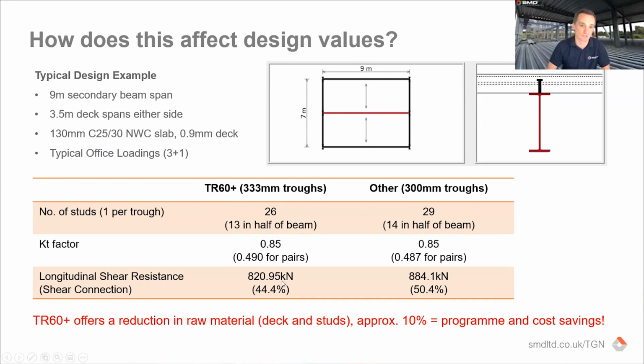What does that mean in terms of the shear resistance for that beam in half of the beam span? And you can see, because you can get more studs on at 300 centers, you end up with a higher shear resistance than you do with 333 centers, but your shear connection is still well above the minimum requirement that was required in this scenario. So with less studs, with less deck material, because our 333 trough product has slightly less steel than the 300, you're still achieving design pass in this scenario, and that's the case for many situations. So by using TR60, you're actually looking at a reduction in raw material, which can lead to potential program and cost savings just by a small number of studs. Obviously, less studs to install, less studs to weld, and a slightly less area of deck involved as well.